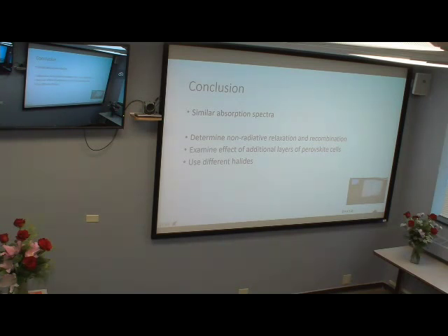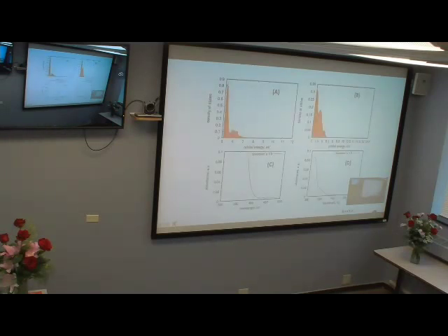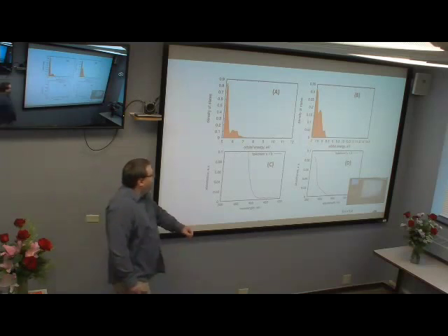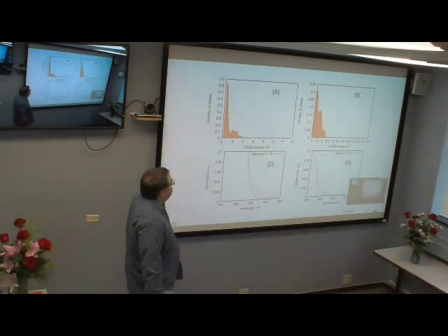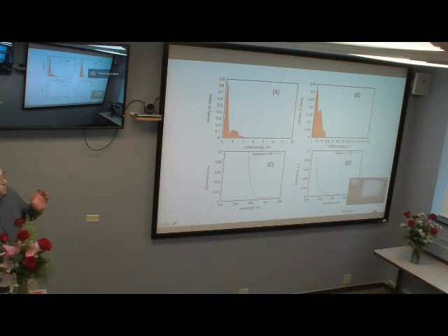Can we go back to your density of states? I noticed it looks like B is a larger gap. B does have a larger gap. It was approximately a 2.8 eV gap for the Ruddlesden-Popper phase, where the hybrid had approximately a 2.3 eV gap. What do you think accounted for that change?